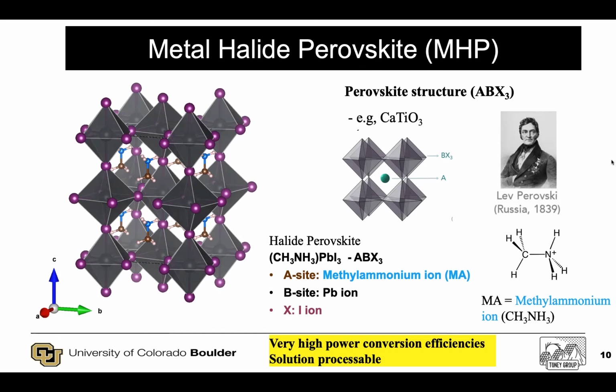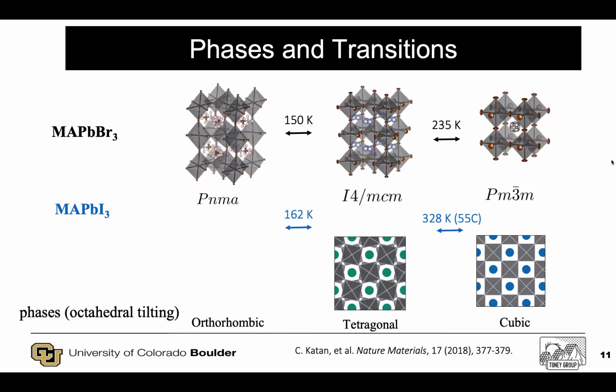The other big advantage that they have is solution processing. So rather than silicon, which needs very high processing temperatures, in principle you can now coat these materials onto whatever the substrate is using environmentally friendly, low energy cost methods. So this has resulted in a tremendous amount of work in terms of understanding the structure-property relationships in these. And that's what I'm going to tell you about, but now in structure.